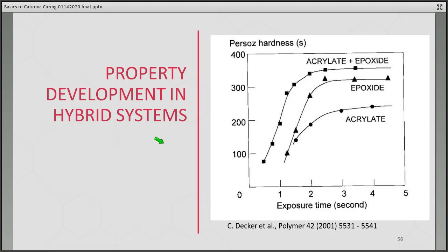Here's a great illustration of how that combination works. So the combination is better than the individual components. This is work done by Christian Decker back in 2001, where he looked at an acrylate system. On the y-axis is the hardness, and there's exposure time in seconds. So you form a certain hardness here after stable. It takes 3 seconds. The epoxide, cycloaliphatic epoxide system, cationic system cured, you got a great increase in hardness.